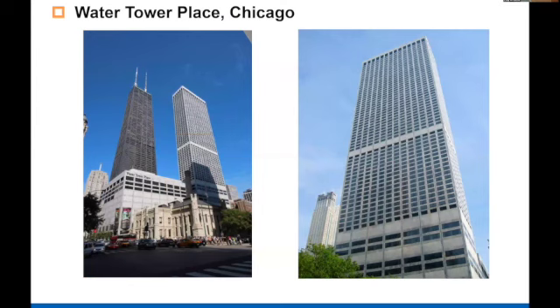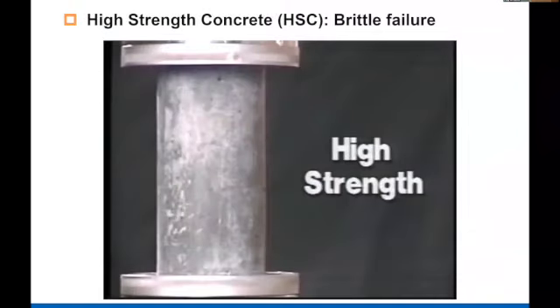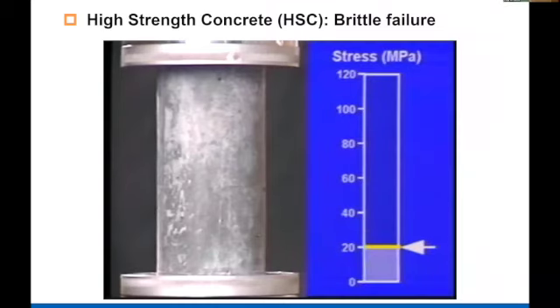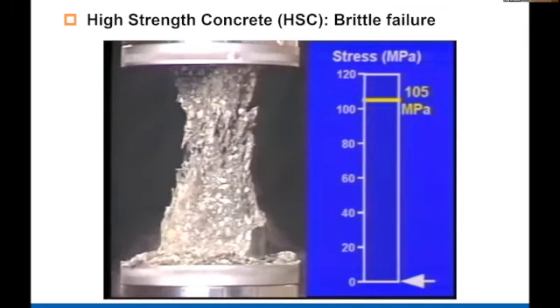My interest in so-called high strength concrete started with the construction of Water Tower Place, an iconic building in Chicago, designed by Skidmore, Owings and Merrill. The material supplier said that we can give you high strength concrete, and at that time high strength was about 50, 60 megapascal or 9,000 PSI. They said, okay, show us how strong you can make it. So they went to the laboratory and tested a concrete cylinder of high strength concrete. You can see this goes up to about 100 megapascal, but the failure was very brittle.